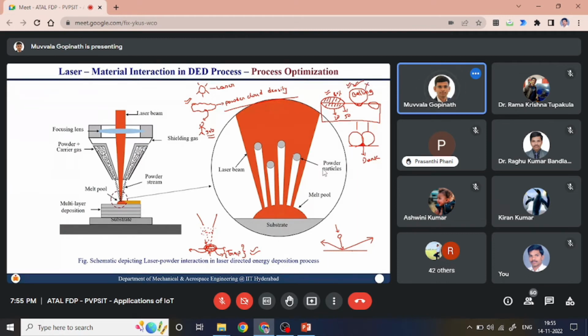This is not good. And if your proper parameters are not controlled, then most of the energy will go into the substrate, melting the substrate excessively. Like let us say 80% is substrate melting and 10% or 20% is deposition. This is also not good, because you are excessively remelting the substrate or the previous layer.